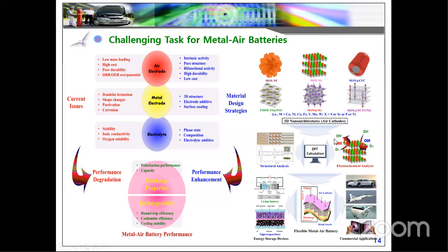Then we need to perform the theoretical calculation, the theoretical calculation confirmation, and the structural analysis. After structural analysis, when we see a binding energy near zero and a very high intense peak, we can choose that material as more active for OER, ORR or HER properties. That's why we first optimize the material, and then we perform 3 electrode system tests for OER and ORR properties. Finally, if these 3 electrode systems are good, we can go for fabrication.